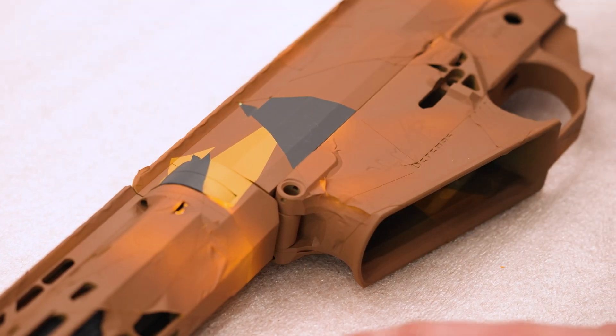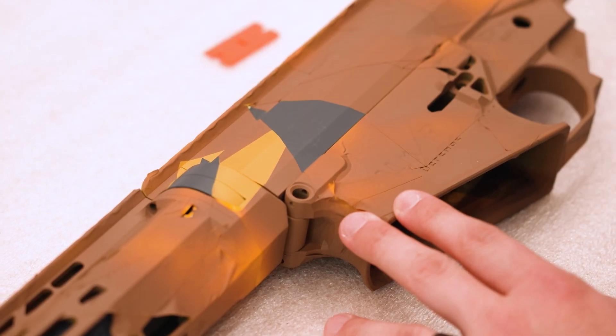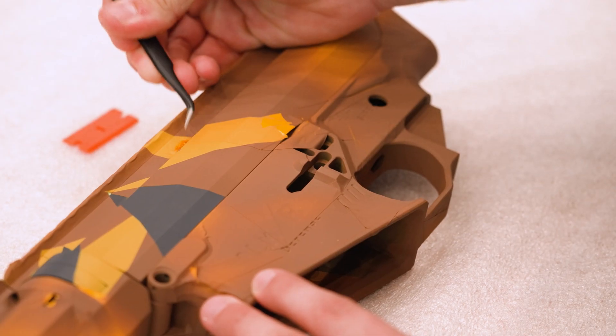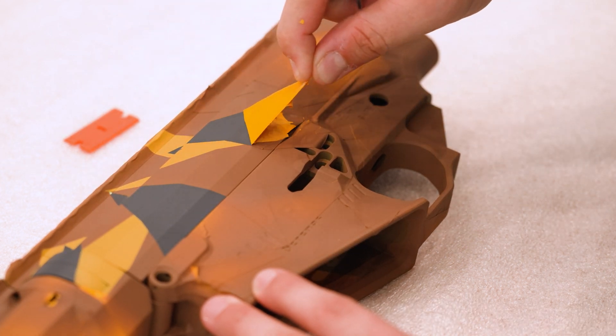Removing stencils. Finally, when it comes time to remove the vinyl stencils, patience is key. Pulling stencils too soon can lift the top coat or underlying coating layers. It's important to allow the coating to set by letting parts reach room temperature. Then you can carefully lift a corner or edge with tweezers or a plastic razor blade, and pull the stencils off at a shallow angle.